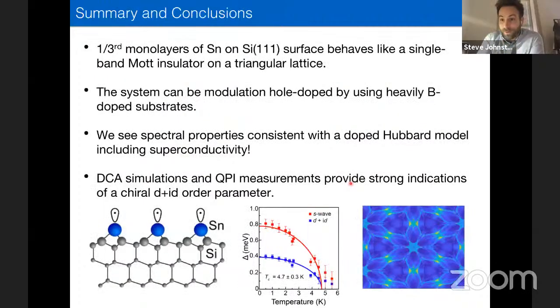All right, so with that, I'll wrap up. As I said, I hope I've convinced you that the third of a monolayer of tin grown on silicon really behaves like a single band Mott insulator on a triangular lattice. I've shown you that these can be hole doped using modulation doping schemes, and this gives you really clean doped Mott insulators. We see spectral properties that are consistent with unconventional superconductivity. And the combination of the DCA simulations and the QPI measurements is giving us a really strong indication that this is a chiral d+id topological superconductor. And so with that, I will stop and take any questions you might have.